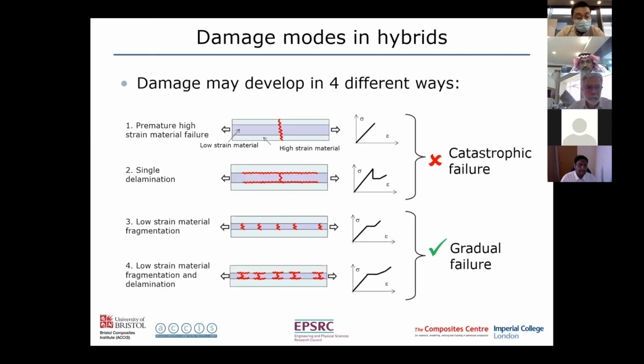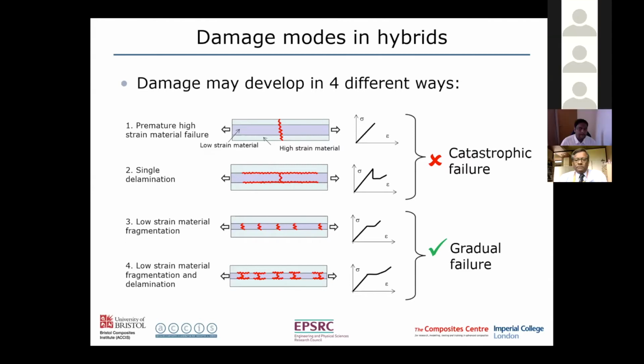So how do we do this? Well, we have to consider the different damage modes that we get in these hybrids, and we have to design it the right way to get this behavior. So if we have too much carbon, then what happens is when the carbon breaks, the glass will break as well, and we'll get a catastrophic failure. If we put a bit less carbon in there, when the carbon fails, then we'll get a delamination at the interface, but again, we'll get a sudden load drop, which is not what we want.